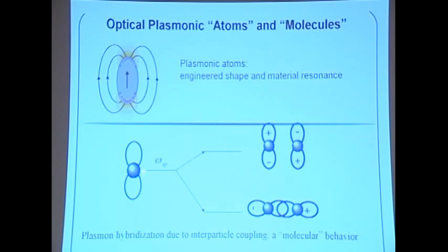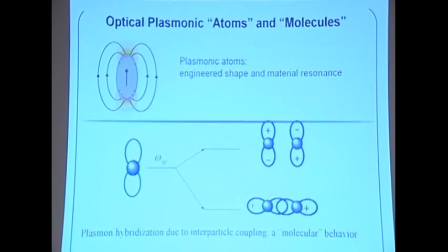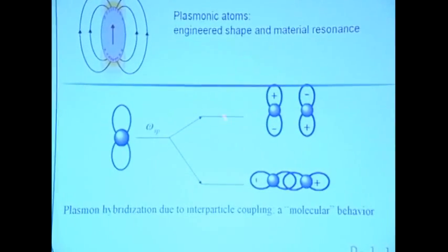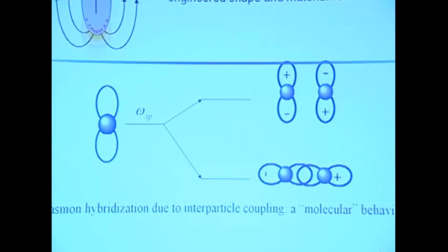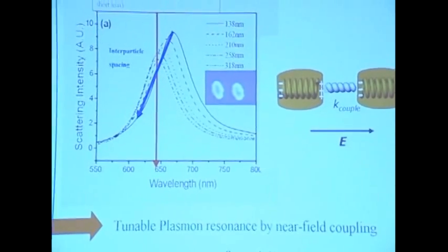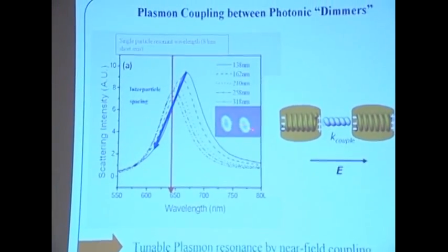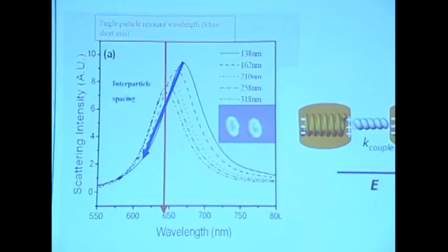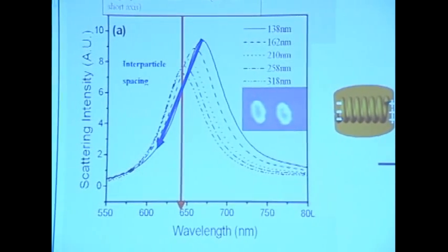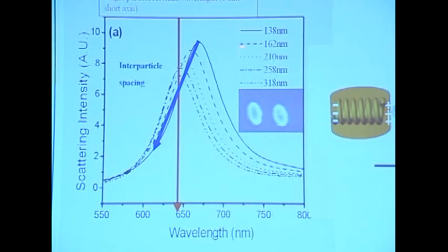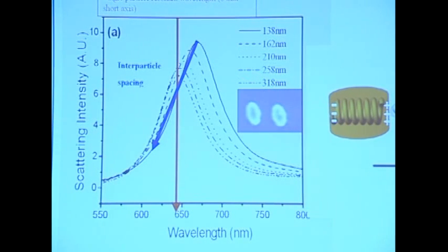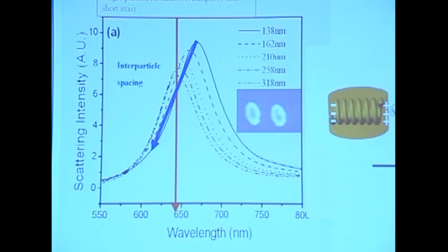Now, if we have a plasmonic atom, in this case a nanometallic particle, for example, which can also be a magnetic particle as we design, then depending on how they interact, different interactions give you different energy levels, similar to an atomic system. So about 4 years ago we studied two metallic particles, writing them with E-beam at different distances. We spaced them from 100 nanometers all the way to 300 nanometers, and looked at what the total system resonance looks like.